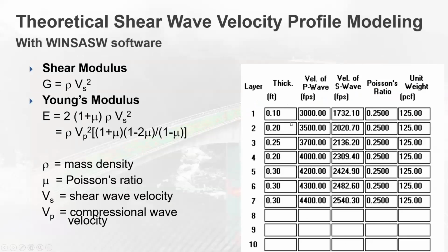And we did that by inputting the layer thicknesses and velocities of the shear wave with the Poisson's ratio and a unit weight for the masonry. Out of this information, from these velocities, you can calculate both shear modulus, where that's rho times the shear wave velocity squared, and Young's modulus, which is 2 times 1 plus Poisson's ratio times the shear wave velocity squared times rho. And rho is mass density, unit weight over gravity. So from this information is how we adjusted the theoretical model to match the experimental data and get the layering, the thickness and the velocities, and really the modulus.